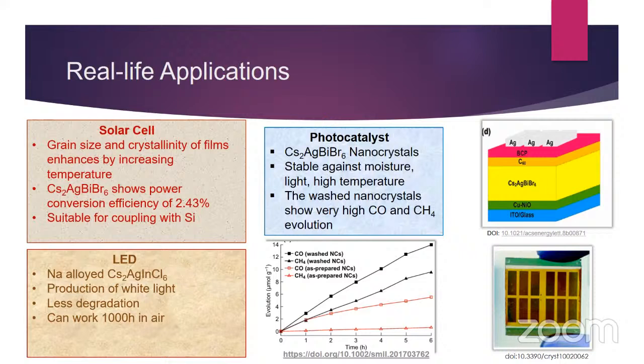Also, double halide perovskite nanocrystals can be used as photocatalysts. Basically, these photocatalysts react with carbon dioxide and finally break it into carbon monoxide and methane. The Cs2AgBiBr6 nanocrystals are stable against moisture, light, and high temperature. From this graph, you can see that between the crude and the washed nanocrystals, the washed nanocrystals show better efficiency for methane and carbon monoxide evolution. And here are the diagrams of solar cells fabricated with Cs2AgBiBr6.